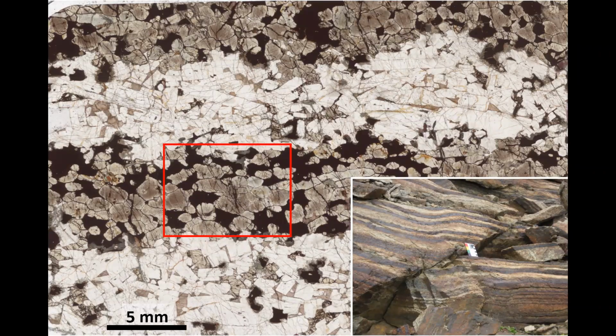And the evidence for this comes actually from some of the non-patterned modally graded layers in these trough bands. So this is trough band G, and you can see these modally graded layers are what Neil Irvine calls bipartite. They're not smoothly modally graded. They are bipartite. You've got a mafic layer and then a felsic layer, black, white, black, white. So this is just a scan of one of those modally graded layers, bipartite. So there's the base and there's the top. It's in two parts. And we're just going to zoom in on this bit here.